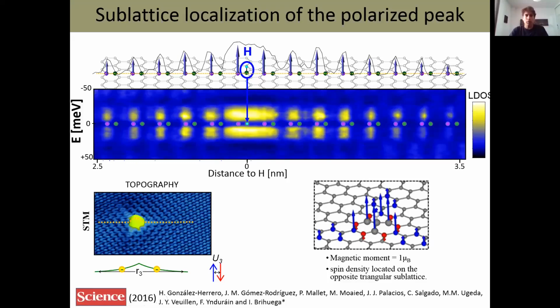So what our experiment shows is that we have a magnetic moment which emerges on graphene. It has a really large extension, so this is more than 6 nanometers, but it goes more than 10 nanometers. It's really, really extended. But the whole thing, according to theory, has one magnetic moment. It's the same magnetic state. So it's a really, really extended magnetic state compared to what you have in standard magnetic materials. Now it is very appealing, of course, to investigate the coupling between the magnetic moments introduced by different hydrogen atoms on the same sublattice or on opposite sublattices, since we will have direct magnetic exchange. But this is already older work, and I won't show the details today. If you want, you can find them in this publication.